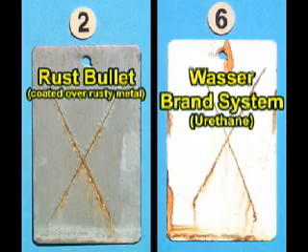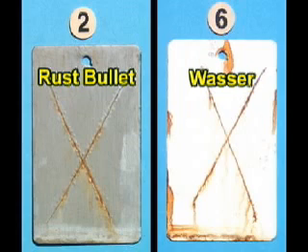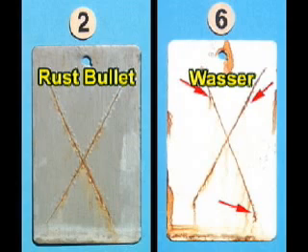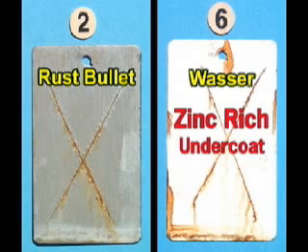This panel is coated with the Wasser brand system. This is the second best test panel in the series and represents the peak of old technology. Significant rusting and undercutting is taking place at the hole and the edges, indicating the difficulty of the system in covering sharp edges and corners. The scribe line is undercutting as well. Like the Rust-Oleum cold galvanizing compound, the three-step Wasser process utilizes a zinc-rich undercoat that provides a degree of galvanic protection. But the use of a zinc metal undercoat brings along with it most of the problems of a zinc-rich primer system.